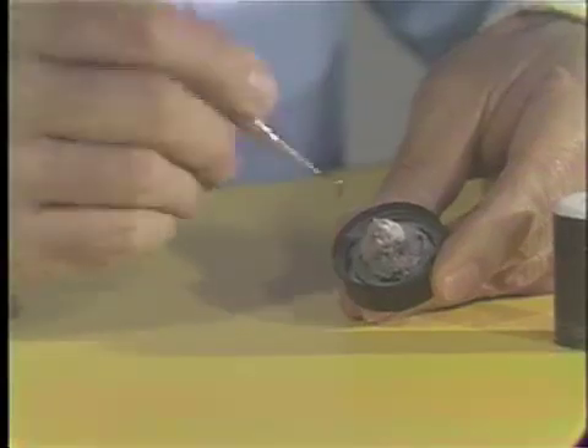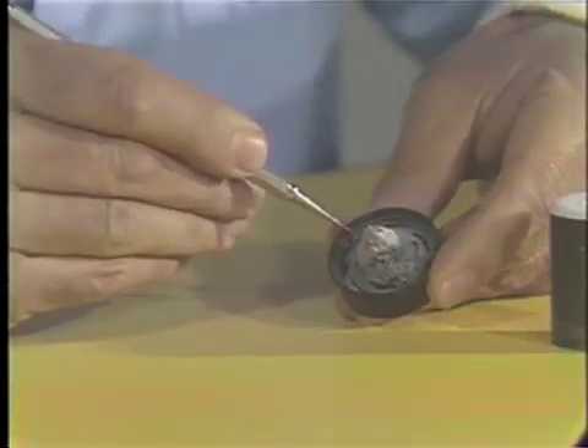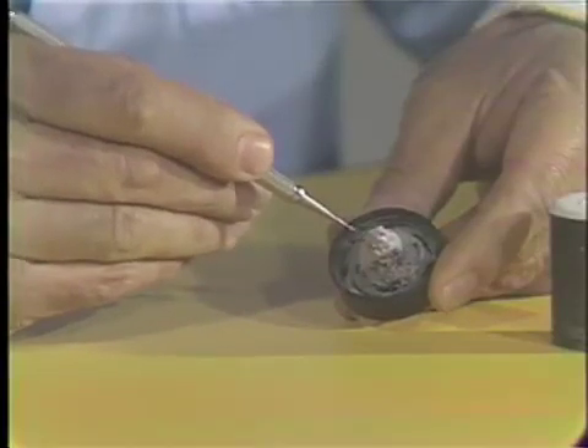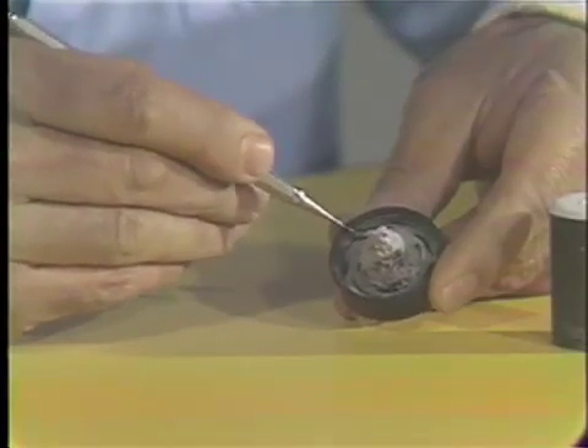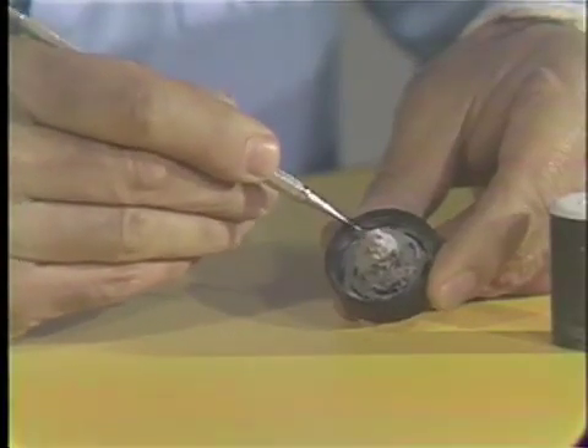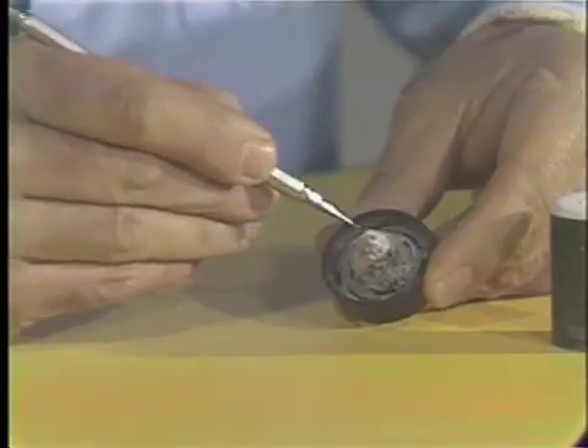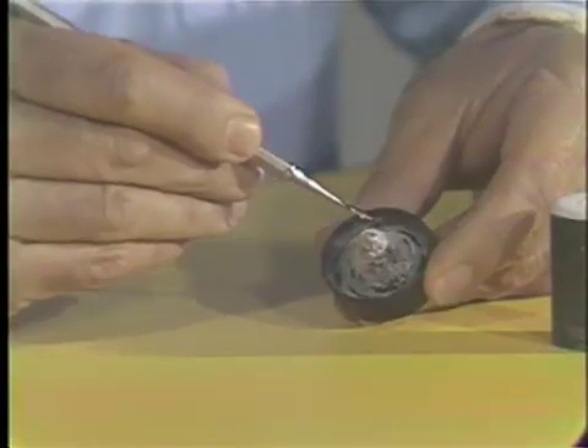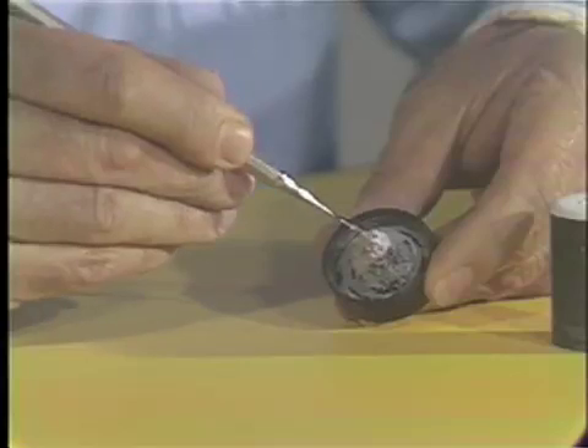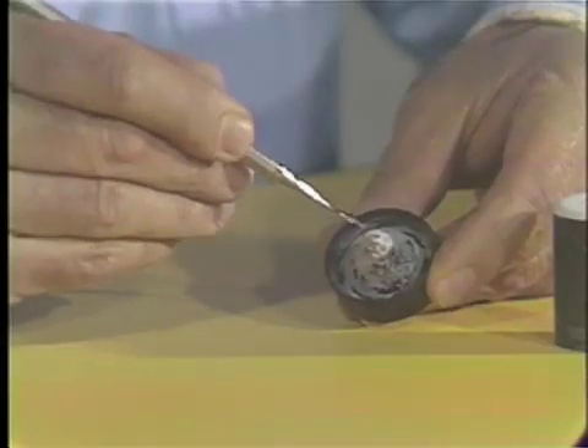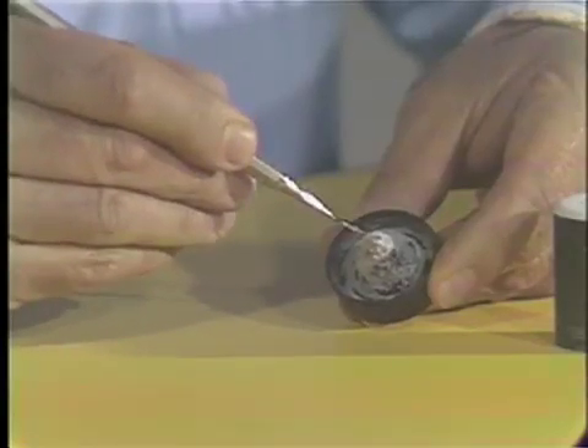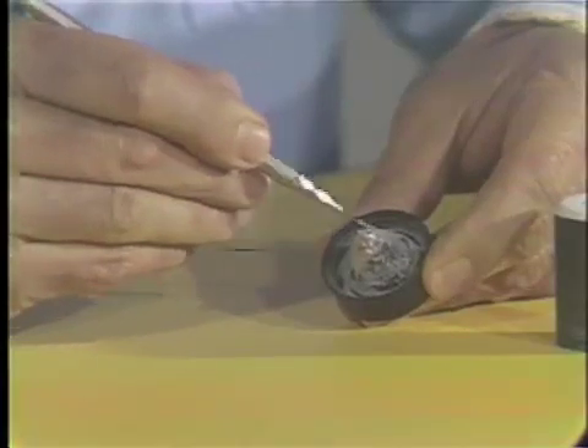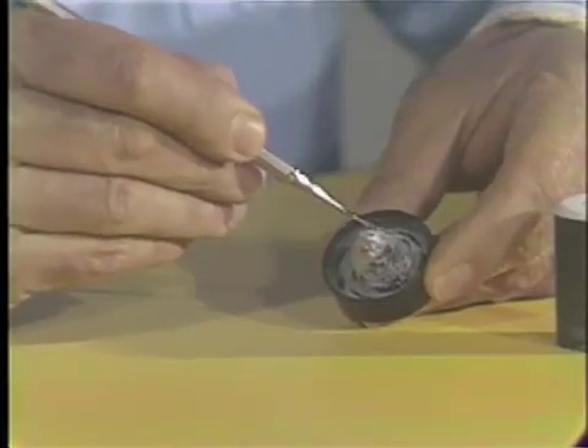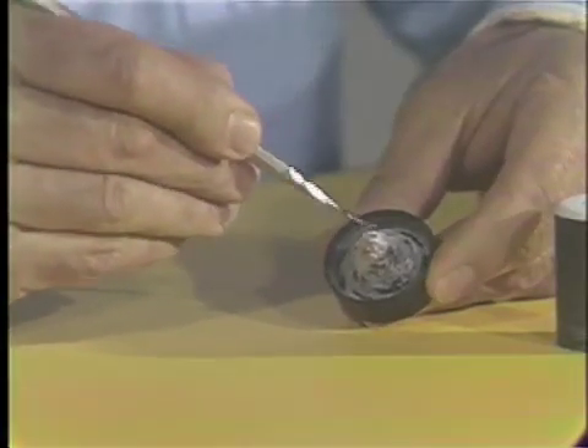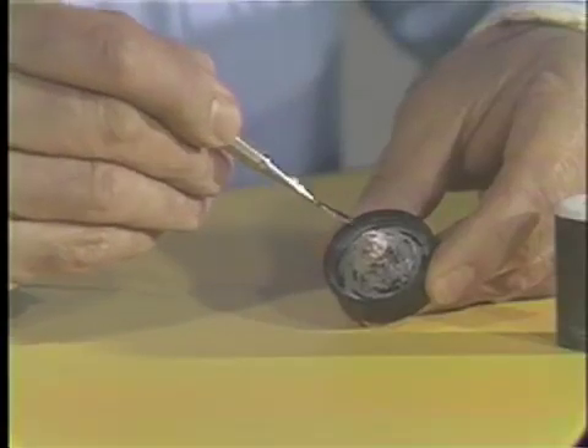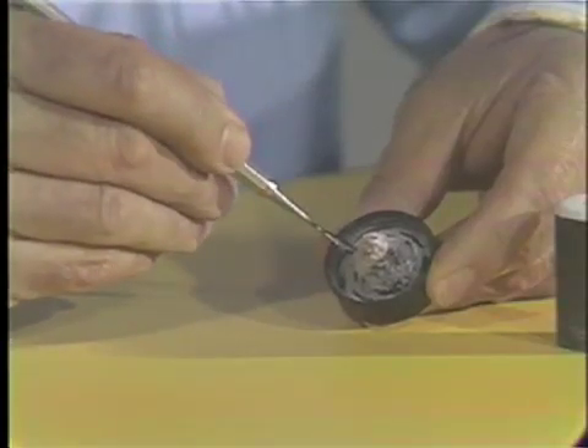And these fine particles of the investment that you see in here, they are loose particles, and if I do not clean them before reusing them, then they will get in the way. They will go into the sprue, through the pattern, and then the gold casting will have some inclusions. It is very important to have these things cleaned before reusing them.